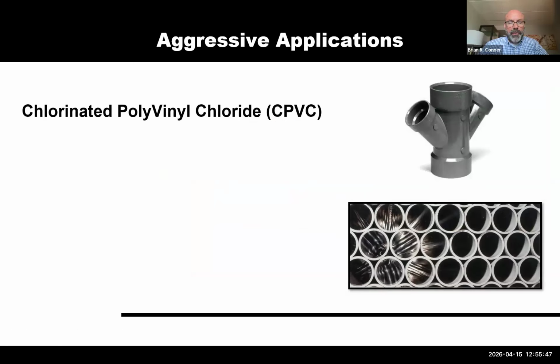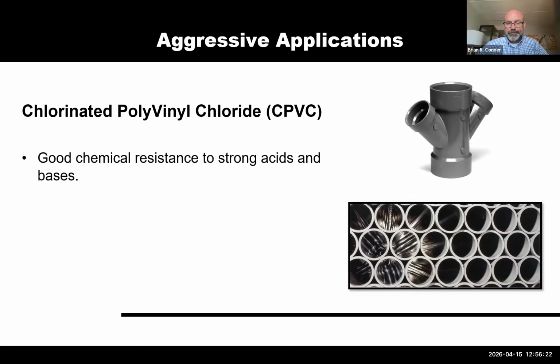Because it can handle those hot temperatures like cast iron. CPVC can handle up to 104.4, so even above that of what cast iron can handle. The problem is that there is no CPVC pipe for standard DWV. We manufacture a CPVC pipe for chemical waste. It meets CSA B181.3, but it does not meet CSA B181.2, which is the standard for plastic DWV piping.